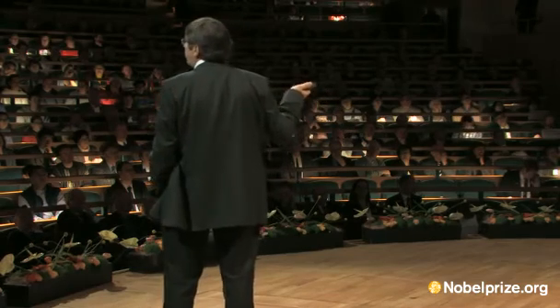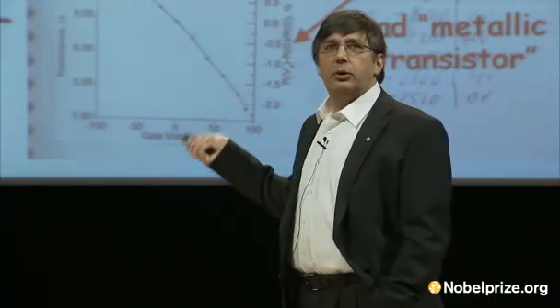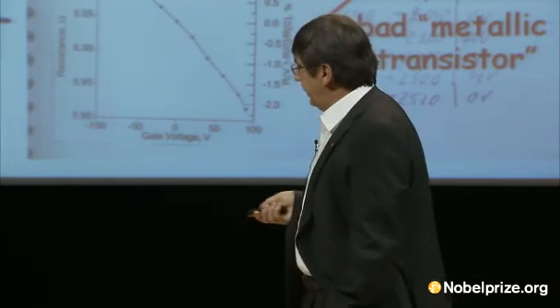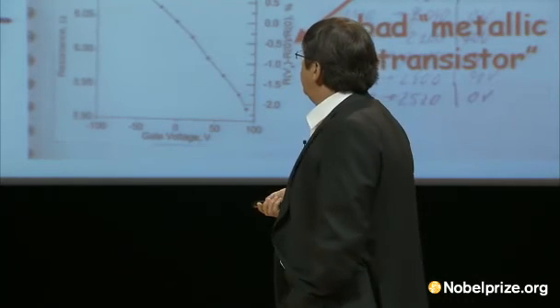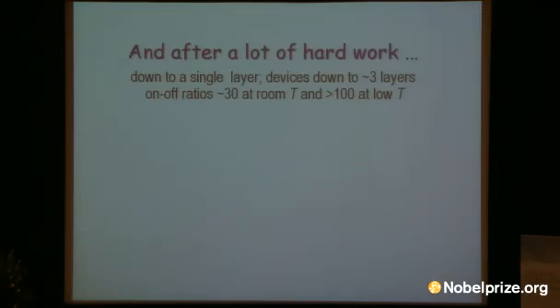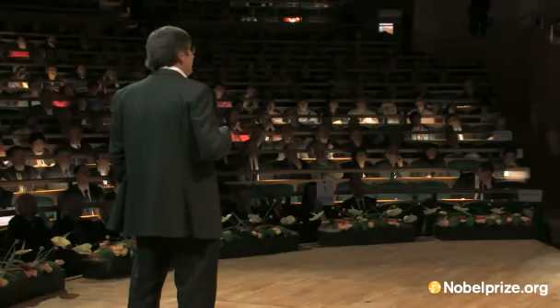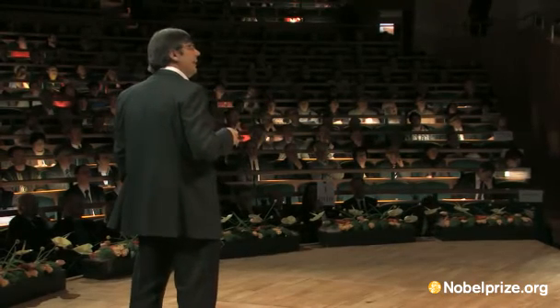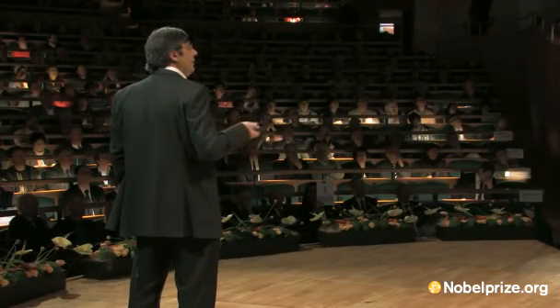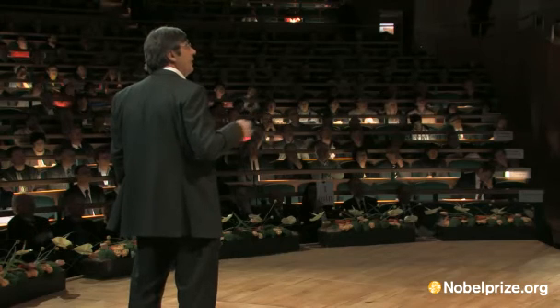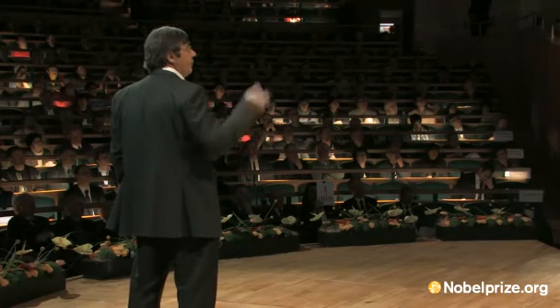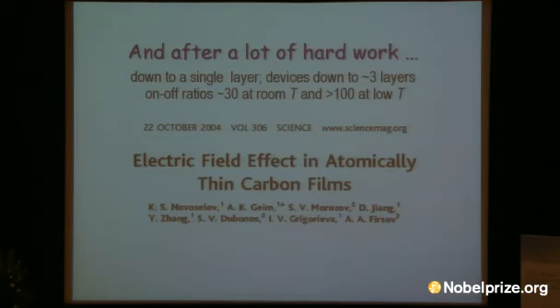And I thought, what would happen if we apply the whole range of techniques we have available in the lab, including lithography? That took quite some time, and within a year we went down to a few layers, and a little bit later down to a single layer. They showed not a few percent, but a 30% ratio, and we published it in Science. It was a hard job not only to do that, but also to publish.